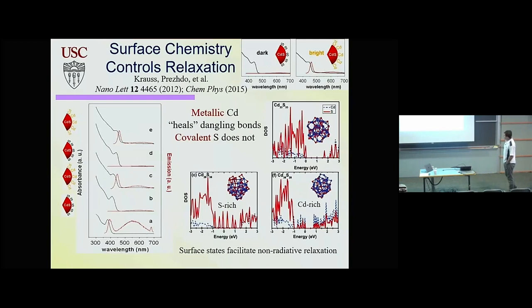So what he saw in this experiment was that he would make a cadmium sulfide quantum dot with two precursors, and those two precursors you can mix in different ratios, or you can add them later. He would make a quantum dot and see emission, which is the red line, and the red line has a peak which follows from the particle in the box model, but there's also this very broad feature that already shows up in a realistic system that you cannot predict by a particle in the box model. But what's even more interesting is that if he adds the precursor that has sulfur, he totally quenches luminescence. At least the main peak disappears, but this peak, which comes from defects, continues to appear.